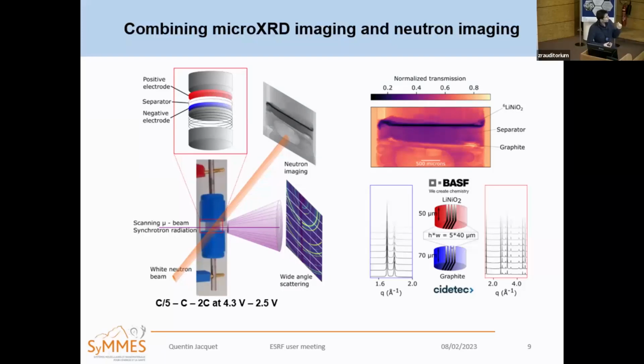You have a microbeam and you scan it along the electrodes, both the anode and the cathode. This schematic represents how we're scanning our electrodes. We're taking this 5 by 40 micrometer beam and scanning in the depth of the electrode and moving around the electrode to limit damage. For each pixel, we get a diffraction pattern, and from that we can indirectly get the lithium concentration.